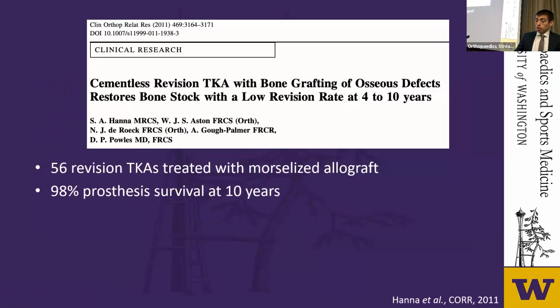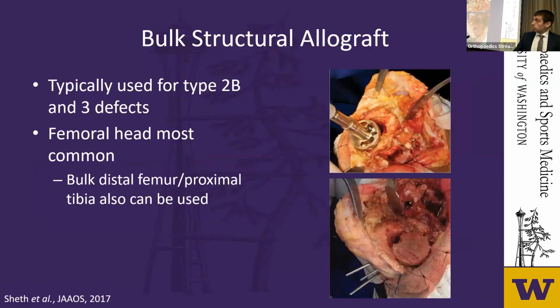This is another well-established technique. This 2011 study published in CORR found a 98% rate of prosthesis survival at 10 years in patients treated with impacted morselized allograft. Once we start moving on to our larger bony defects, specifically type 2B and type 3 defects, we start getting into cases where we're going to need either bulk structural allograft or supplemental metal prosthesis augments of some form.